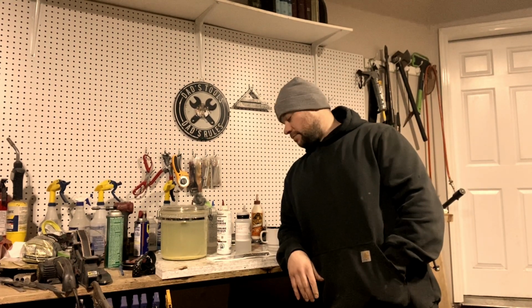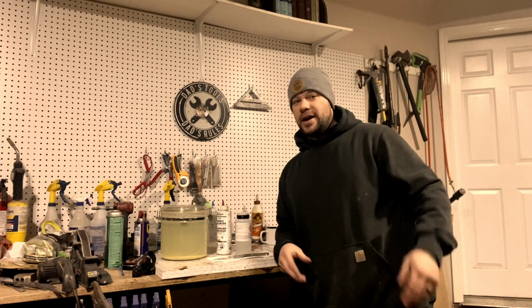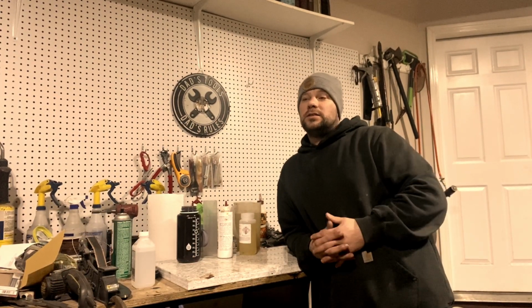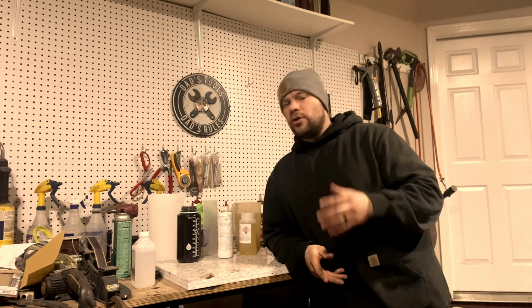And I think it's important to talk about etching, because etching Wootz is not like etching your modern Damascus. Etching Wootz can probably be the most tricky part of the whole process. You go through all this work and polish up your blade, and then you etch it and it doesn't pop like you want it to, but that's just how it goes. I've already etched this blade. I did a test etch at 120 grit, so I know what to expect. And there's some things that happened, and I'll talk about why they happened.